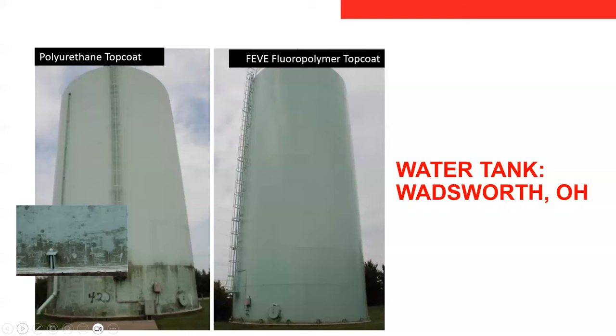Dirt pickup is another one that we encounter a lot. And this is really the ability of the film, again, to not degrade over time and be able to clean or somewhat self-clean depending on the weather that's in that location. So in this case, this is a standpipe of a water tank that's in a public park. And you can see where it has a lot of condensation on it because of the cool water and humid air around it. And the bottom portion of that has a lot of growth, mainly because of just lawn clippings and some of the maintenance activities around that tank that are landing on it and starting to provide organic matter for mold and mildew to grow. So it's very unsightly, especially in a public park.